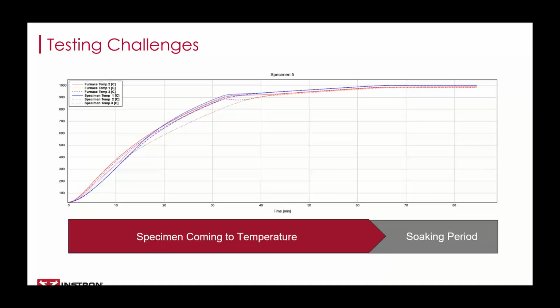Regardless of the standard body you're adhering to, whether it be ASTM or ISO, your lab is going to face the same obstacles as anybody else in the industry doing an elevated temperature test. A core requirement that is very clearly outlined in ISO 6892-2 and ASTM E8 is the requirement to meet soaking criteria. These standards state that your specimen must reach a specified temperature before the test begins. Once your furnace controller or testing software indicates that the specified temperature is met, that specimen temperature must be held within a tight tolerance